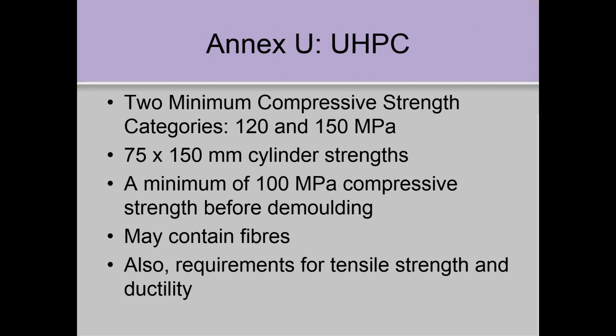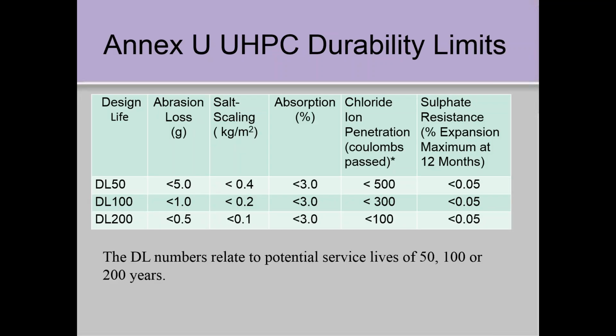And you typically keep them in the molds till they're at 100 MPa. Some of these ultra high performance concretes contain fibers, in fact quite a few of them, because a lot of the requirements also include tensile strength and ductility requirements. So it's not just the compressive strength. So we've got three designations here in that annex, and DL stands for design life. So you have a 50-year design life, 100, 200.